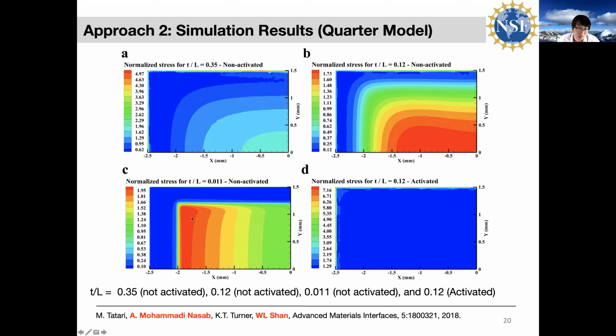Here it will be at the center, and in this case, when you go to really small TOL, it actually starts somewhere between the edge and the center. We did all this calculation in this paper, which I won't go into too much detail. These results qualitatively explain why we're seeing the increased dry adhesion from the mechanical testing results I showed earlier.